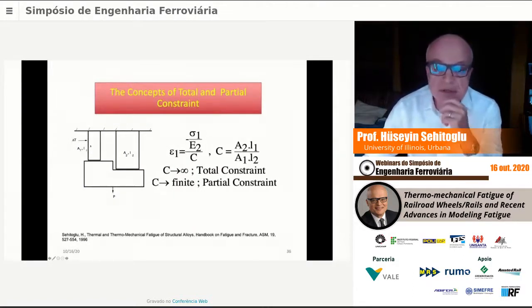If I arrange this equation, I find the total strain in bar one, epsilon 1, which is what I'm interested in. This is bar one, this is bar two, and they are in series. The bar one total net strain is minus sigma 1 divided by the modulus, divided by a big constant C, where C is A2 L1 over A1 L2. It comes from those equations. If A2 to A1 is a very large number, the material is more or less totally constrained, and epsilon 1 is practically zero. C goes to infinity: total constraint. But if C is finite, then we have partial constraint.